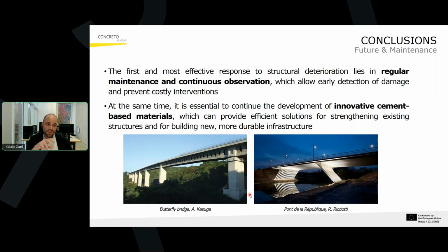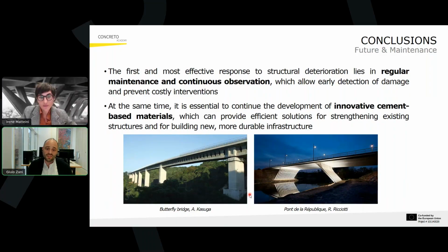And the last message I leave you here is that at the same time, it's essential to continue with the development of innovative materials, because this will be the basis for the retrofitting of existing structures, but also for the design of new durable infrastructure. And I reported here a couple of examples. One is the Butterfly Bridge in Japan by Akio Kasuga, which uses very high performance fiber reinforced concrete to create thin-walled elements characterized by significant durability. And the other one on the right is the Pont de la République by Ricciotti in France, in which we have a very nice appearance of a bridge because of the high strength of this material, which allowed for the design of very thin sections characterized by a great architectural expression as well.